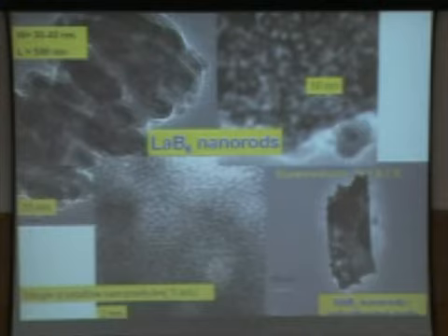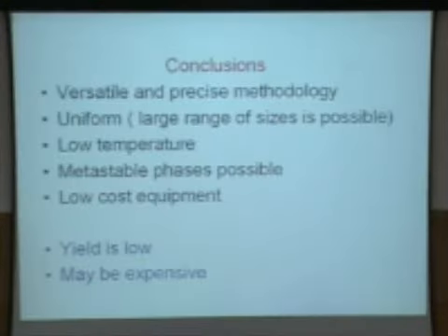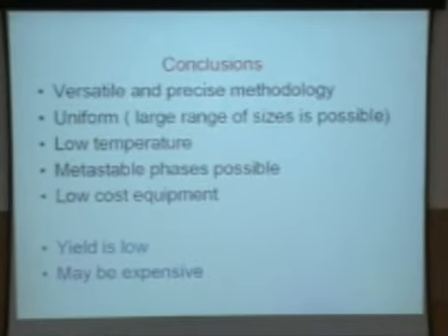So what I want to say for this part is that this technique is very versatile, and you can get very precise morphologies and uniform morphologies at low temperatures. You can stabilize phases which are otherwise thermodynamically unstable. You don't need too much equipment. On the negative side, the yield is sometimes low and it may be expensive. So it depends on the applications what you want.